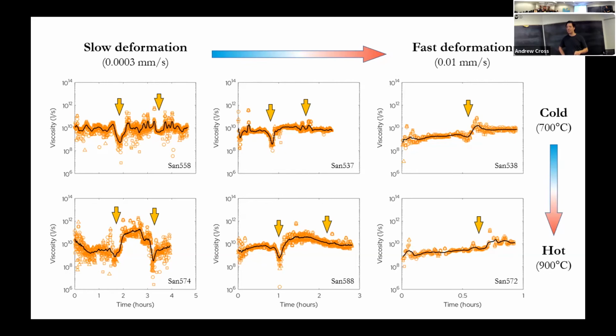And then you get a little dip again as you go back through the phase transition. So we're seeing weakening here, but the magnitude of that is more or less similar at cold and hot conditions. You can see that more with this middle column, where the curves look quite similar really. The amount of transient weakening here is about the same magnitude.